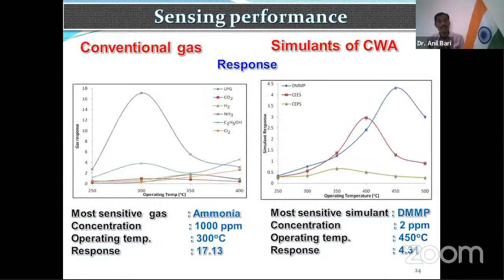Now, this is the actual sensing performance of the conventional gas as well as simulant of the gas. So in the first graph, we show the operating temperature versus gas response. The exposed gases were LPG, CO2, H2, NH3, chlorine, and ethanol. Among all the gases, the most sensitive gas was observed to be ammonia at a concentration of 1000 ppm at an operating temperature of 300 degrees, giving a maximum response of 17.13.